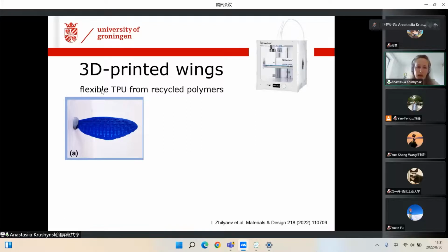Okay. Then we decided to check if it is possible to produce these wings. And for that, we used a dual nozzle 3D printer and flexible TPU material made from recycled polymers. And we ended up with having it printed. So you see in the variation of colors here that in certain parts, the wing is very thin. So it contains just, to be more precise, 2 printed layers of material. And this ensures the wing flexibility.